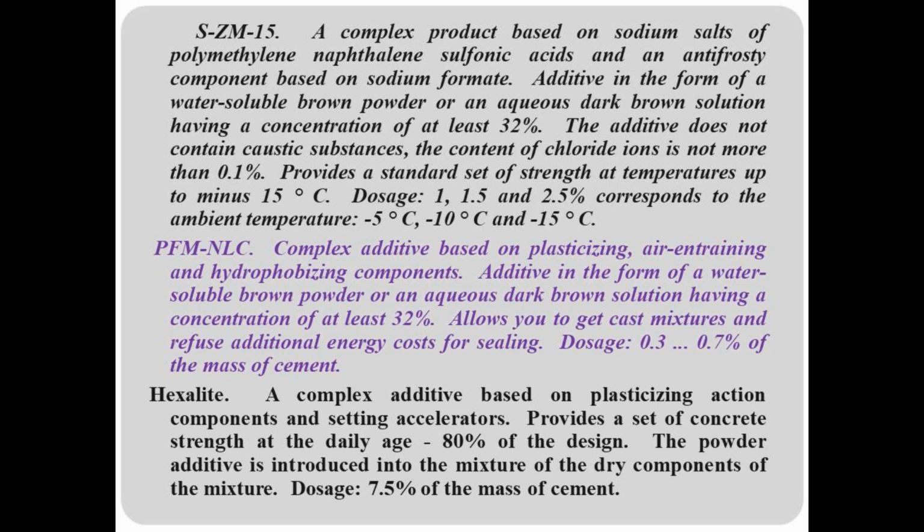Provides a standard set of strength at temperatures up to -15. Dosage 1, 1.5 and 2.5% corresponds to the ambient temperature of -5°C, -10°C and -15°C.